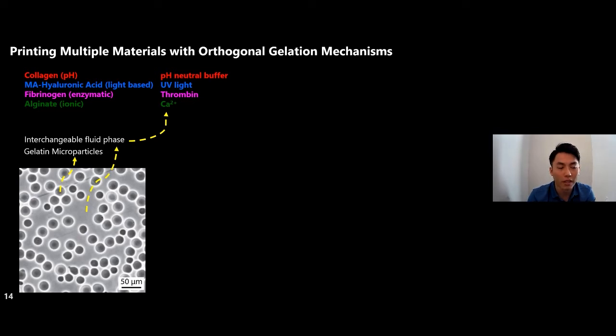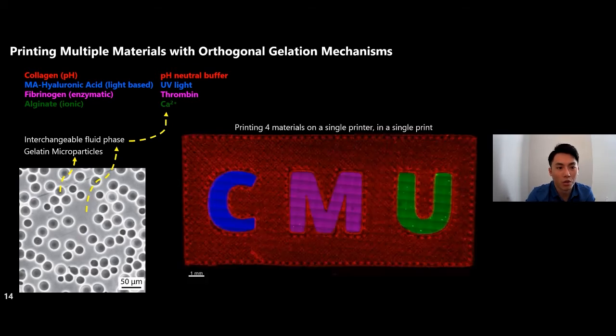We can shine a UV light towards the support bath. We can add in thrombin. We can also add in calcium ions. And so you can start to see why all of these could occur within the same support bath. And then shown here on the right, we actually printed 4 materials on a single printer in a single print. So this all happened with the 4 materials that we described, inside a single print.